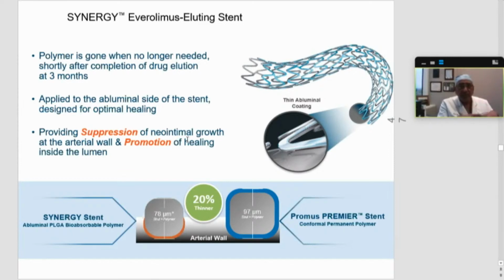So as you can see on the left side, you've got a photo cartoon of the Synergy stent, which is 78 micron thick with an abluminal layer of a bioabsorbable polymer. And the Promus Premier, which is our current metallic DES, has a 97 micron thickness with an all-around polymer. You can easily make a case for what's the need for polymer on the endoluminal side of the artery.